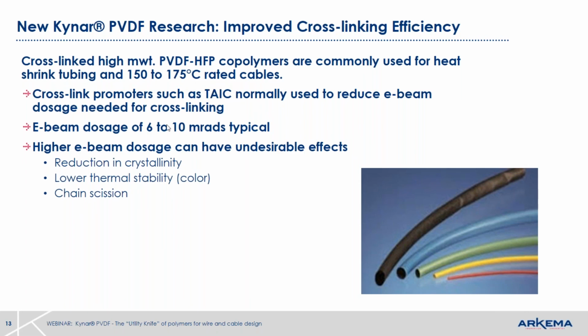Without TAIC, you may have to double this dosage, but when you double it, you would reduce the crystallinity of the resin. You would also incur a darker material, and then chain scission would ensue. So our recommendation is always to incorporate TAIC whenever you want to cross-link any PVDF. This is a well-known technology, known for many, many years.